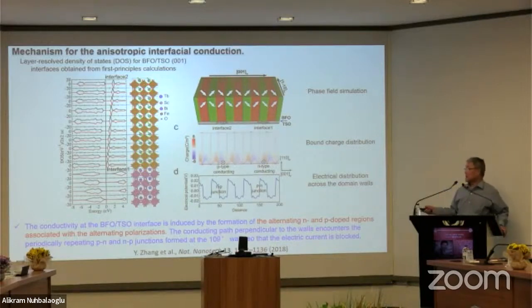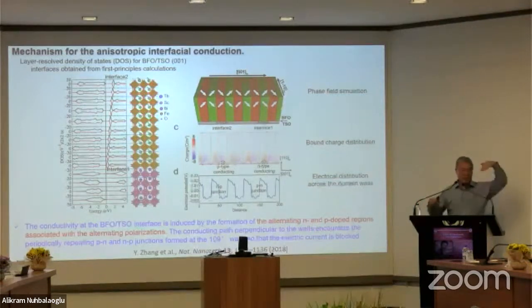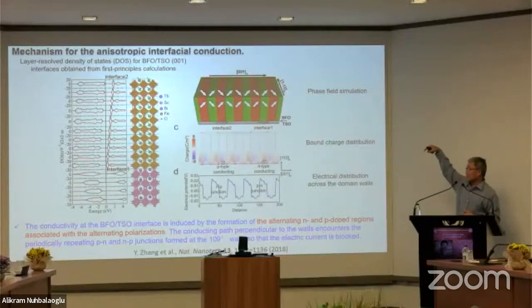Okay, and then we talk about our data and feel really excited, and then you do an additional calculation. You fill the supercells with different thicknesses of ferroelectric. The conclusion is that when the ferroelectric is thicker than 8 unit cells, the band bending at the interface will make the interface either p-type or n-type, and then electrons or holes will be trapped. This will depend on polarization pointing toward the interface or away from the interface. This forms alternating conducting material.